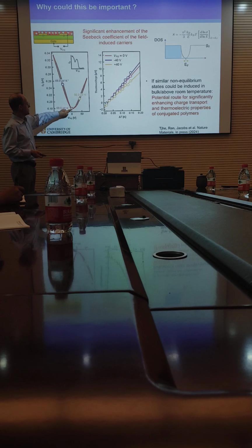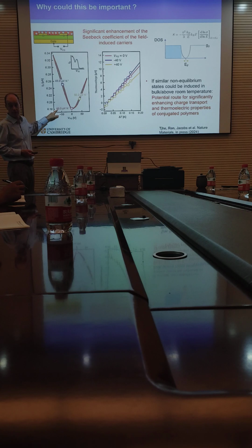And finally, I want to just briefly talk about why this could be important. This is a measurement of the field effect modulation of the Seebeck coefficient. In this case, we make a doped film, and we measure the Seebeck coefficient of that doped film, and then we look at how much the Seebeck coefficient is modulated when we add a few more electrons or a few more holes into the system with the field effect gate. And you can see that here. At zero gate voltage, where there are no extra holes or extra electrons, we have a Seebeck coefficient of 60 microvolts per Kelvin due to the doped film.